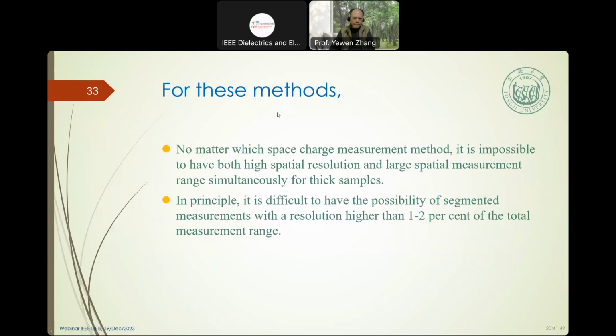For these methods, no matter the space charge measurement, it's impossible to have both high spatial resolution and large spatial measurement range. Scientifically, for a thick sample this is not possible. In principle, it's difficult to have a measurement with a resolution higher than 1 or 2% of the total measurement. For example, if your sample is thick, your resolution should be low. This is a limitation of the measurement principle.